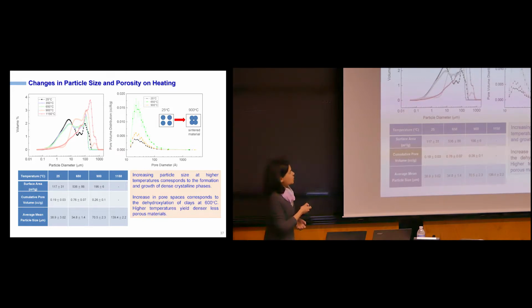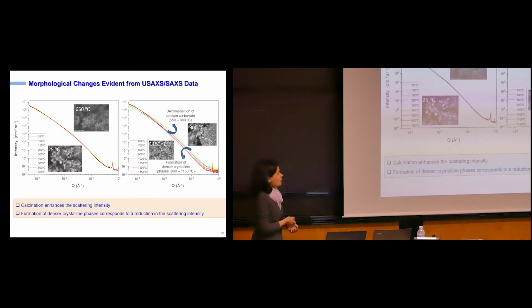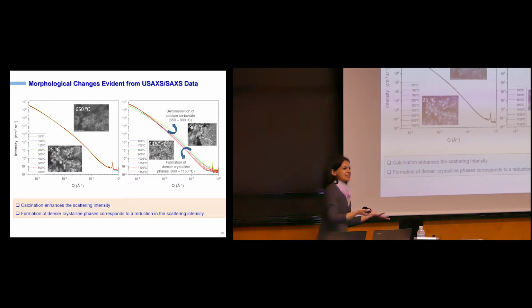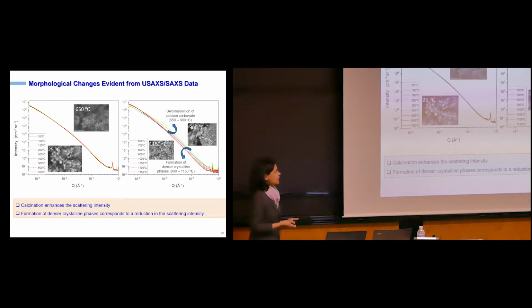And it turns out that when you heat it to 650, you open up the pore spaces because you are basically decomposing the CO2 or removing any water that may be present. But then when you are heating it up to temperatures greater than 700, you're squeezing out the pore spaces, basically causing sintering to happen in the subsurface environments. So some of the engineering phenomena that you actually see in the lab is something that actually happens in the subsurface environments as well.